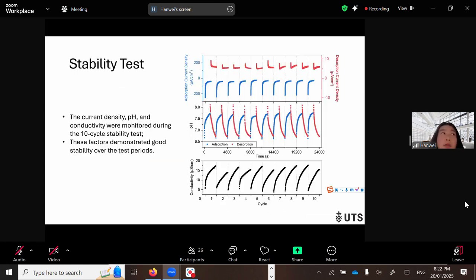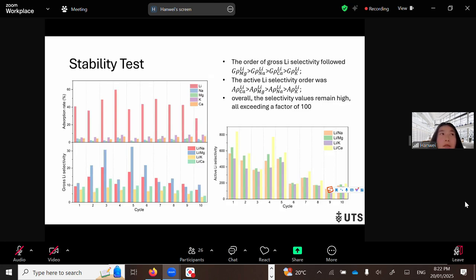And here we also did a 10 cycle stability test. The current density, pH, and conductivity were monitored during these 10 cycles, and these factors demonstrate good stability over the test period. And the order of the gross lithium selectivity follows from lithium-magnesium over lithium-sodium over lithium-calcium over lithium-potassium. But the active lithium selectivity order was lithium-calcium, lithium-magnesium, lithium-sodium, finally lithium-potassium. Overall, the selectivity values remain very high over the 10 cycles, all exceeding a factor of 100.